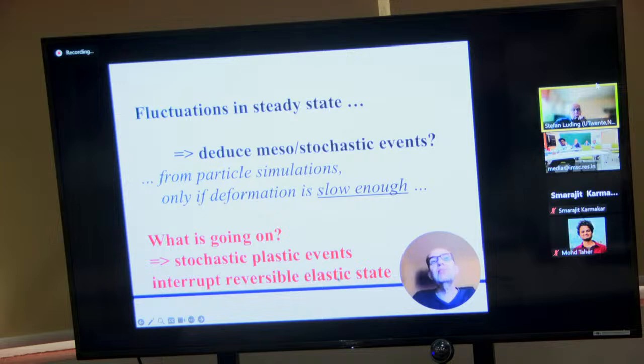Okay, and for this one, you really have to go slow enough. Most of the time in finite size systems, experiments, you have too many particles and you cannot go that slow. In simulations with small system size, a few thousand particles, 10,000, 20,000 particles, we can go slow enough, we have to be patient, but then we can distinguish the stochastic plastic events which interrupt the reversible elastic state.